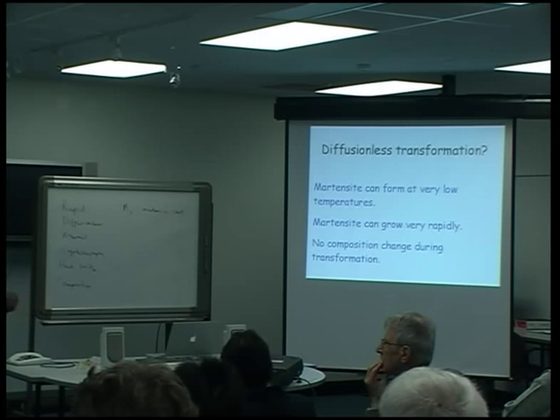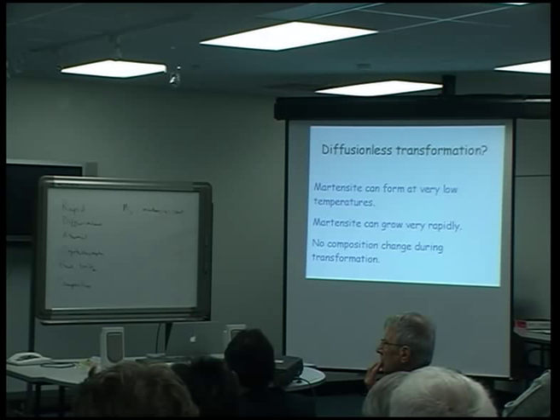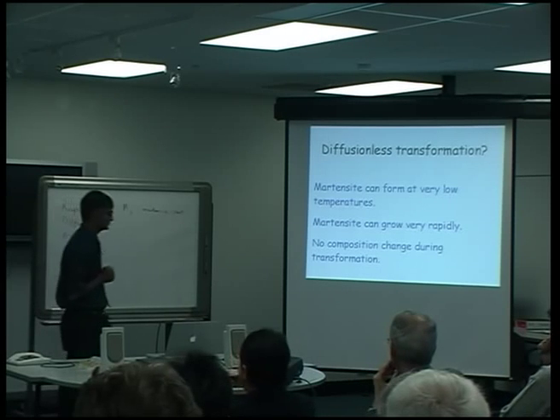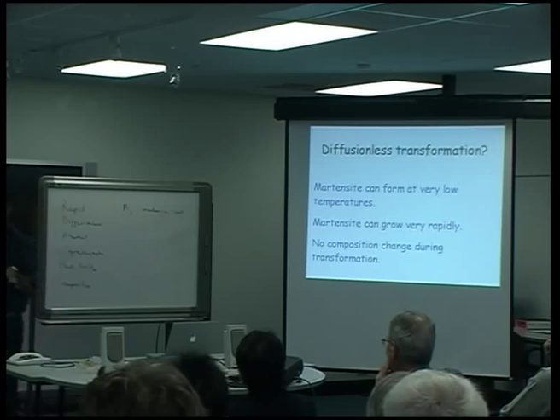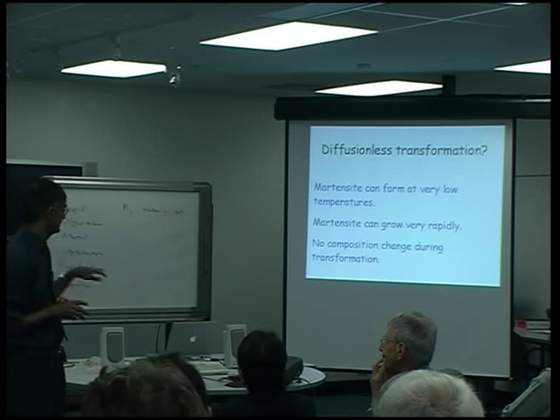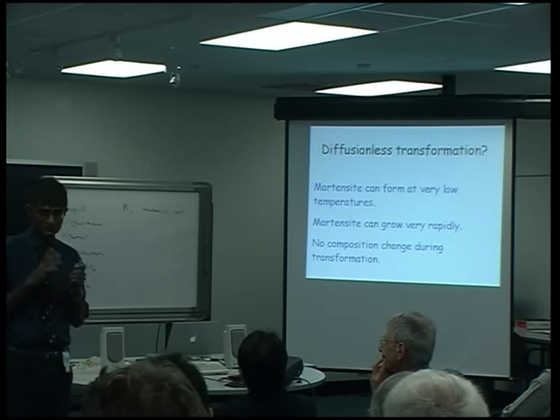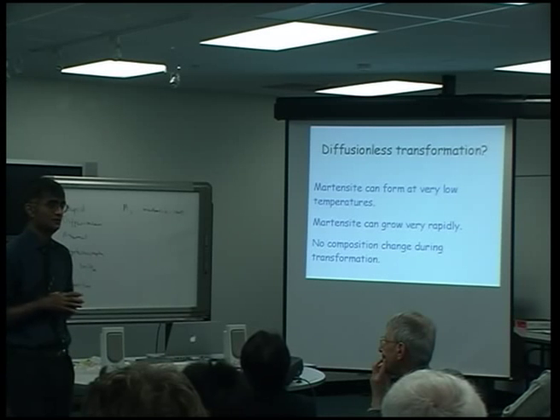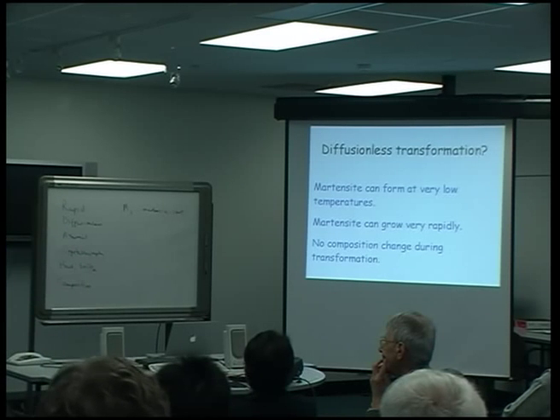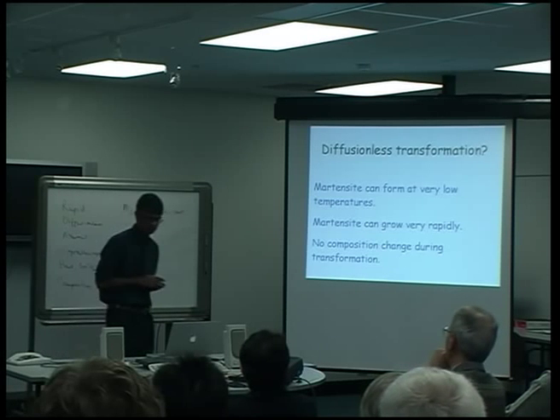The transformation can happen so rapidly that it emits sound — if you search for 'singing' on my website, you can hear the song of martensite; it sounds like a chorus of bells. You can also measure the chemical composition of martensite and show it's exactly the same as that of the parent phase. That is a necessary condition, but not sufficient — we can get a transformation without composition change even with diffusion of atoms. All of this indicates a diffusion-less transformation with no real controversy.